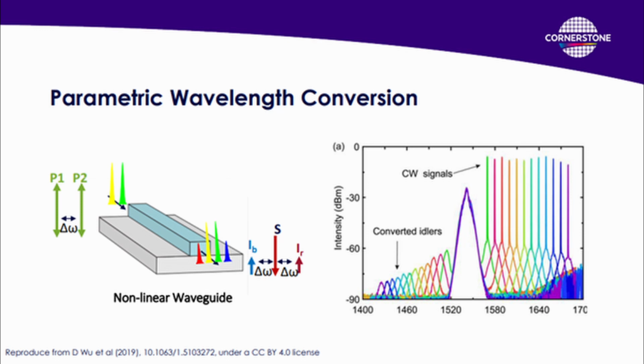So in this case, you could put a signal close to 1515, you could use a pump close to 1515, and then by tuning your signal, you will be able to generate new signals called the idlers at shorter and longer wavelengths. And why is this useful? The reason why this is useful is because by exploiting this wavelength conversion, you can increase the aggregate of wavelengths that you can transmit in telecom and datacom, and start exploiting other wavelength bands that haven't been exploited so much because we don't have the lasers, but there are low loss fibers that can transmit these wavelengths, like in the 1600 regime.